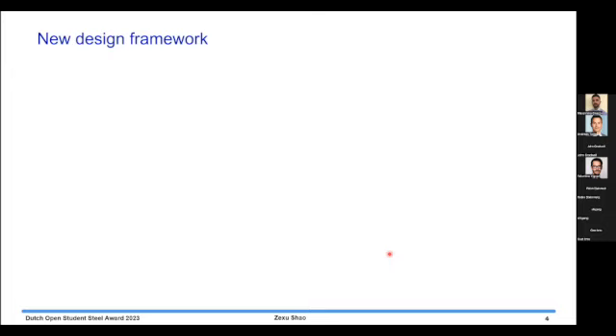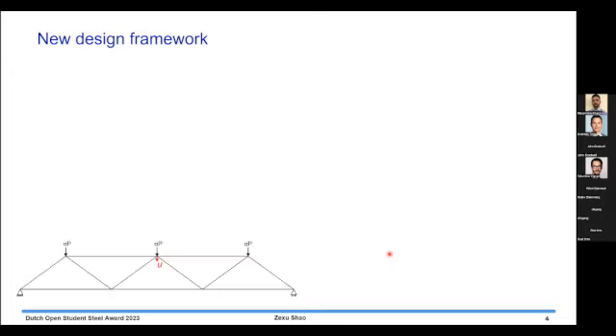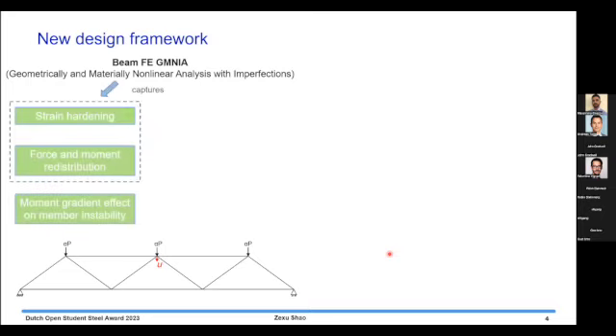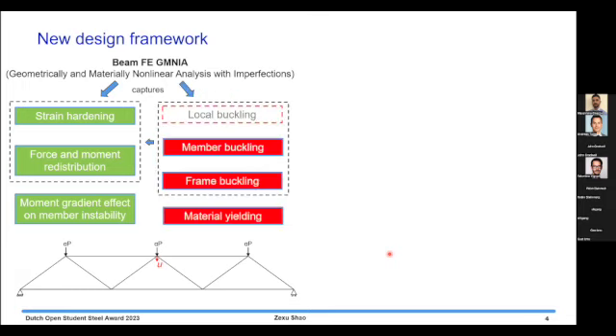Now for steel truss design, we can carry out a beam finite element GMNIA analysis, and the analysis itself can capture the beneficial effects of strain hardening, force and moment redistribution, and moment gradient effects on member instability. But the extent of these beneficial effects is very dependent on the failure point. The model can predict member buckling, frame buckling, and material yielding. But at this point, as we are not able to predict anything about local buckling, we cannot say whether the predicted result is safe or not.